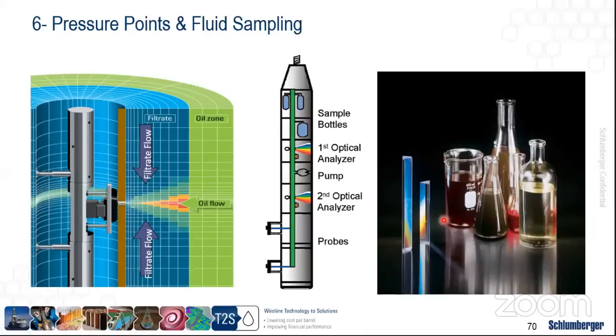But for sampling to happen, we need to start pumping at a very high rate instead of just relying on the very small chamber or volume that we have, which is 20 cubic centimeters in terms of pressure points. We need bigger bottles or bigger flow lines in order to get the virgin fluid. So we're using the same probe, the same type of tool, and the only thing added is another set of tools above it, which has a bigger flow line. It has a pump, where we start pumping and try to clean the formation of the mud filtrate in the invaded zone.